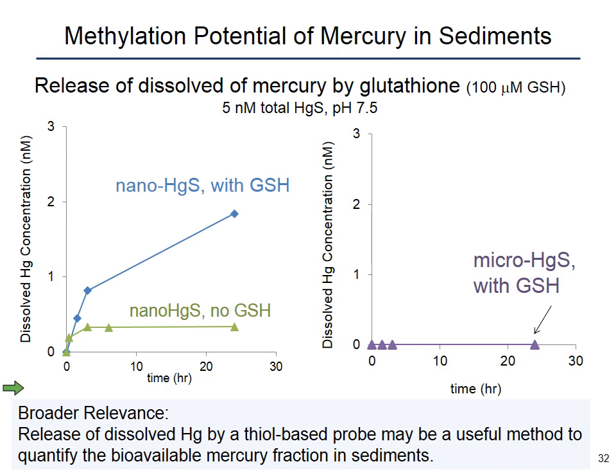Okay, so here's a result from our experiments with the nanoparticles, where we're comparing nanoparticles and microscale particles, where we were not only interested in their methylation potential, which I showed that the nanoparticles are greater in methylation potential relative to microscale particles, but we were also interested in differentiating between their reactivity, particularly a reactivity with a thiol compound like glutathione. So what researchers believe contributes to the mechanism of uptake in microorganisms is that mercury binds to some kind of thiol or sulfhydryl-containing compound before it is taken up by the organism. So if you look at the reactivity of nanoscale mercury with a thiol like glutathione compared to microscale mercury sulfide, you can see that the nanoparticles are dissolved much more quickly with the glutathione relative to the microscale particles. So the nanoscale particles are much more reactive with the glutathione.